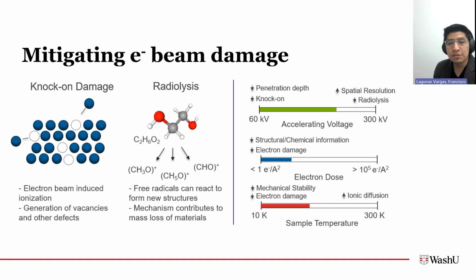So both of these degradation mechanisms are driven by the number of electrons that we put into it. And so we want to have enough electrons so that we can get as much structural information from a material, but not so many that we're actively changing the structure of it. And then finally, as I'll talk about in the in situ aspect of this work, we can play around with the stability of the material by changing the local environment. So in this case, we can reduce the temperature of the sample and therefore try to mitigate some of these